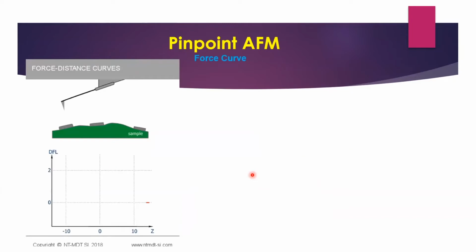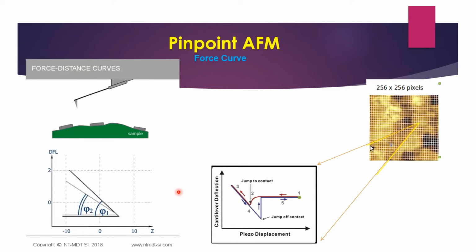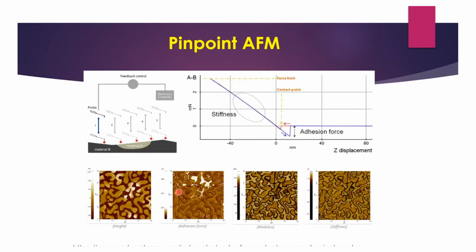Another technique is the pinpoint AFM. This pinpoint AFM was developed to measure mechanical properties in materials, and in this technique you measure the force curve pixel by pixel, and you obtain mechanical information of the sample, like adhesion force, modulus, and stiffness maps.